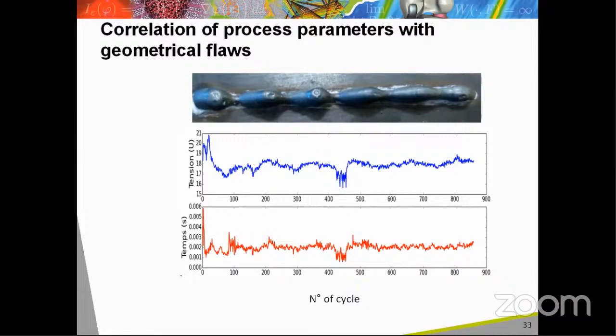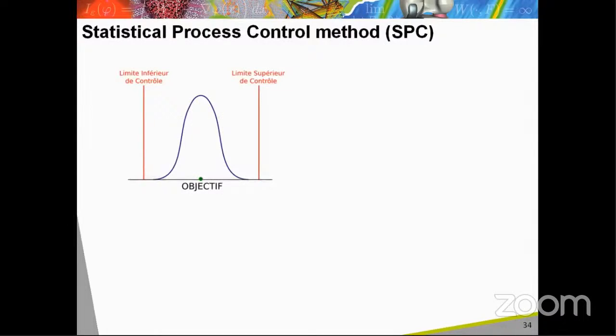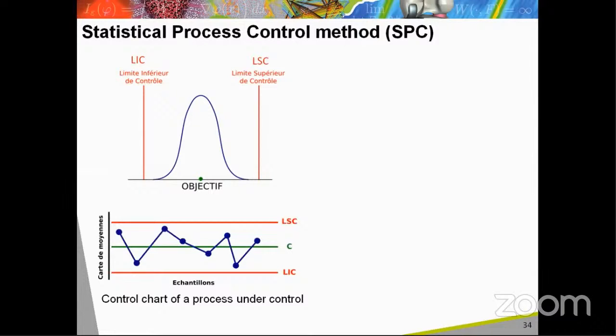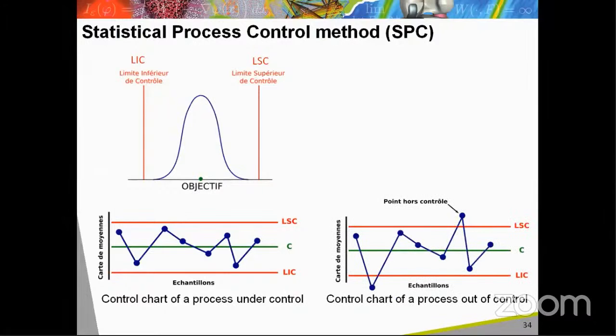In particular, the mean voltage of the wait phase and the duration of the wait phase seem to be correlated to the height variation of the deposits. These parameters can then be monitored in order to detect geometrical flaws on the deposit and to correct the process parameters when critical flaws are detected. For that purpose, a statistical process control method has been introduced. First, the control limits are defined as the process capability for a stable process without geometrical flaws. Then, control charts are computed to follow the stability of the process. A process is under control when the points of the control chart are inside the control limits. On the opposite, a process is out of control when the points of the control chart are outside the control limits.